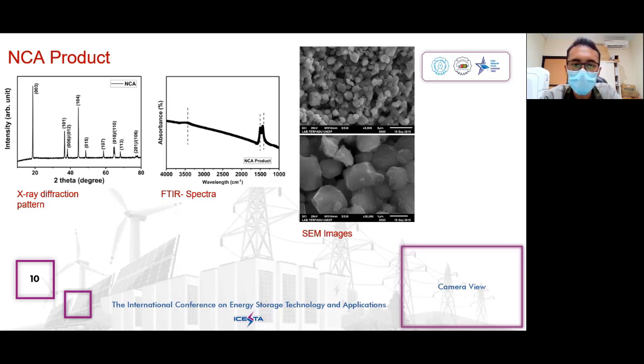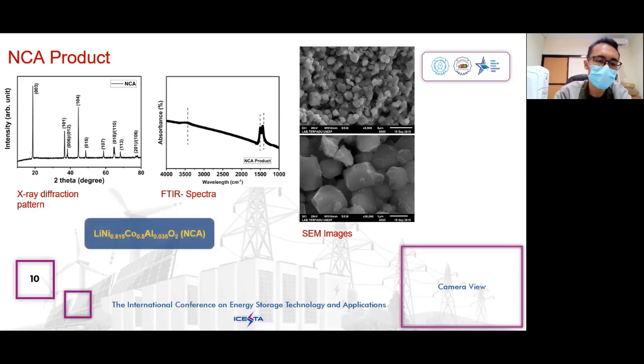The particles have clear edges and a slightly smooth surface after the sintering process at high temperature. The particle morphology is sustained from its original form of NCA oxalate, even though CO2 was decomposed during the calcination process, leaving porous particles. However, high temperature sintering may turn the porous particles into dense particles.